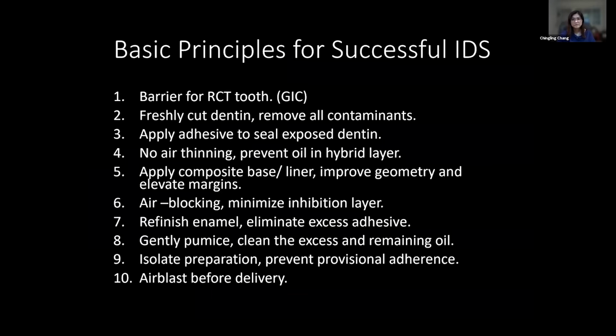So in order to achieve successful immediate dentin sealing, here are some little tips for your reminder. First of all, if we're doing this on a root canal treated tooth, we want to use glass ionomer cement as the barrier, because a lot of root canal sealers actually contain eugenol, and the eugenol will affect the polymerization. So we can use glass ionomer cement to build up a base or liner around the orifice, so we don't need to worry that the eugenol will affect the polymerization of the bonding agent.